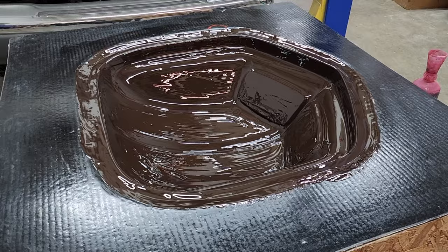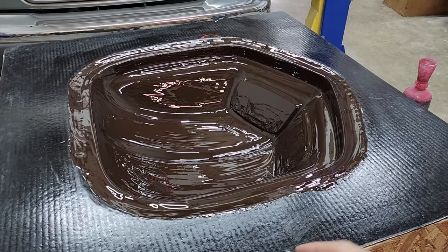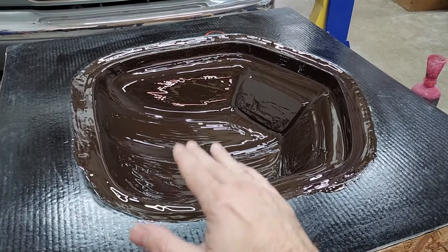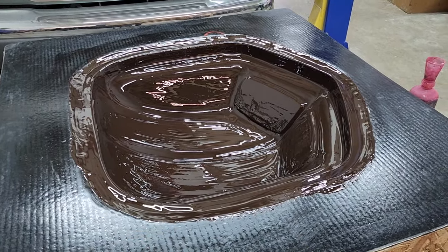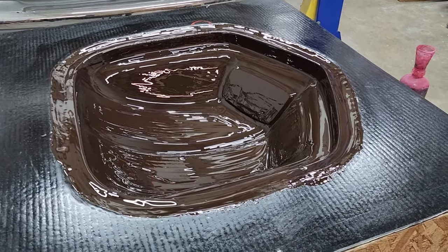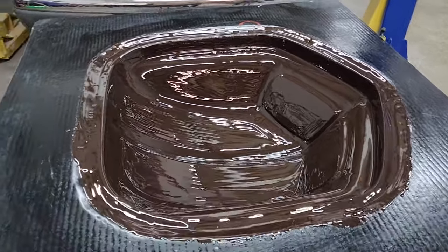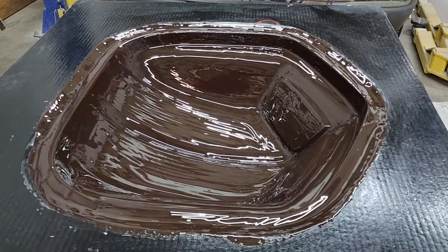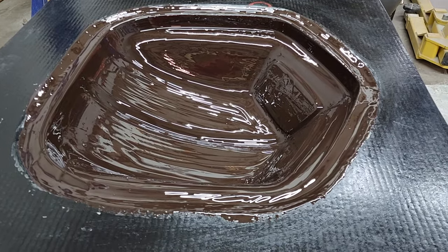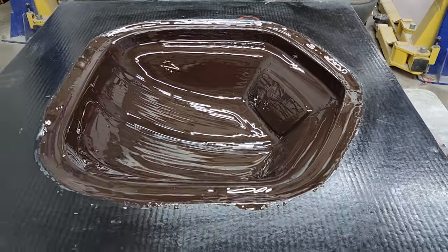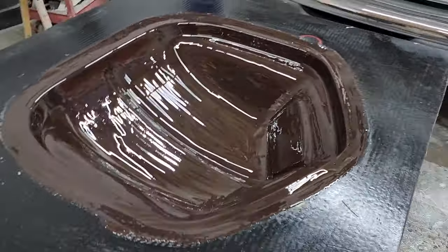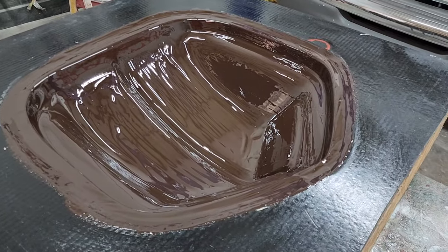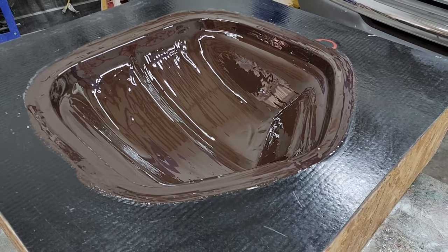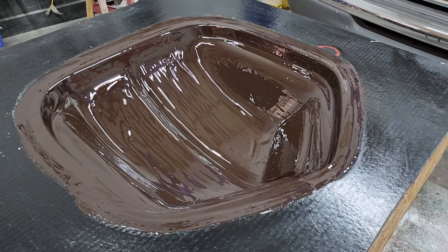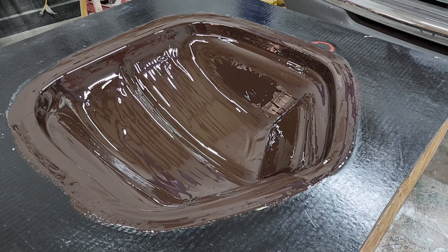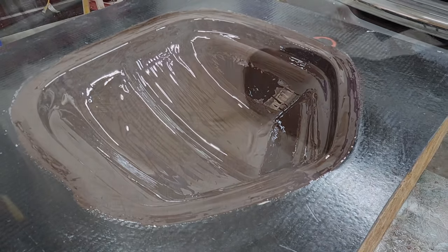If you get into where it's different thicknesses on the mold, it can cause lifting problems where, you know, you'll get like almost a bubble that'll lift off the mold, and you don't want that. So the more consistent you can be, the better, in the thickness of application. So spraying it obviously is the better way to go, but you end up with a lot of wasted material, as well as having to clean a paint gun and all of this. With this process, we only spend about 35 cents with the cup and the brush to get this laid in the mold. So it's a little bit cheaper and uses less materials.